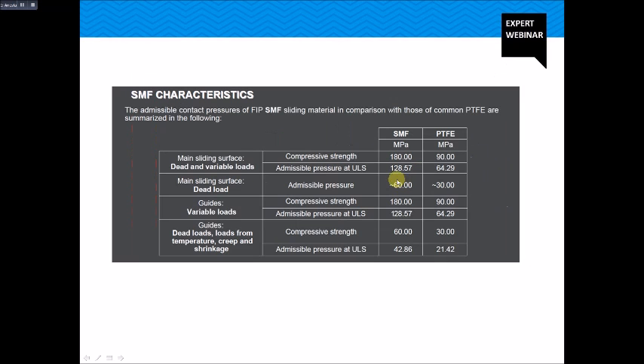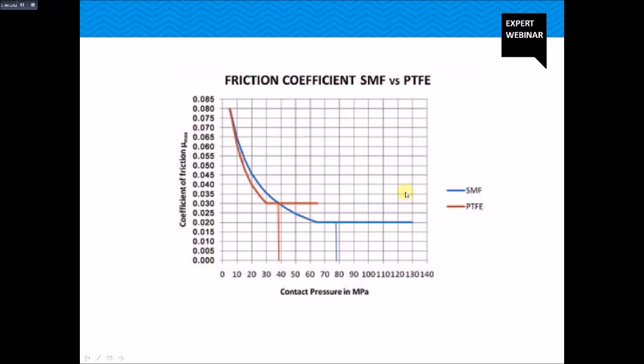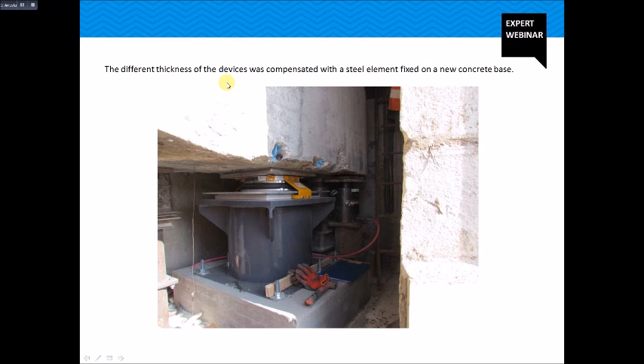In this section we can see where the SMF layers are arranged, and this table compares the admissible contact pressures of the SMF sliding material in comparison with those of the common PTFE, and we can see that they are always double. This diagram compares the friction coefficient of SMF with PTFE. The different thickness of the devices was compensated with the steel element fixed on a new concrete base.